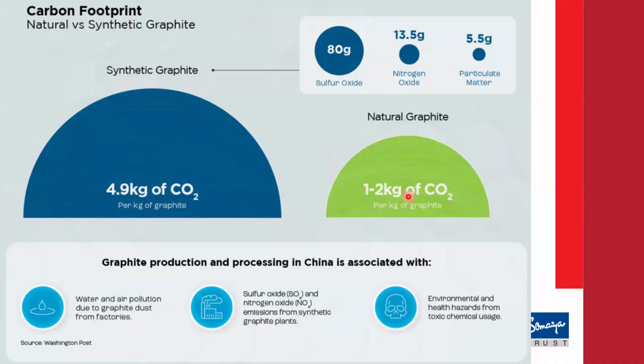Some numbers: natural graphite, I basically expel around 1 to 2 kg of CO2 per kg of graphite produced. If you look at synthetic graphite, which means I'm talking about a hydrocarbon or a carbon precursor, I need around 4.9 kgs of carbon dioxide expelled per kg of graphite. Majorly because when I say hydrocarbon, I usually have a good amount of sulfur associated with it.